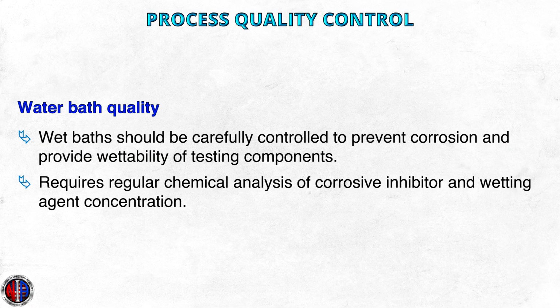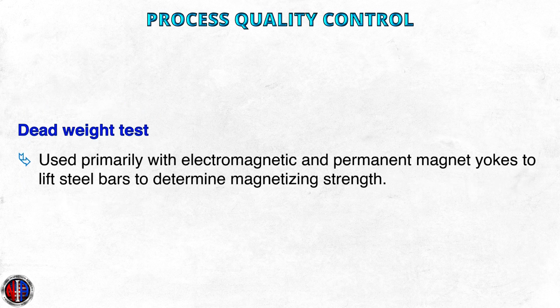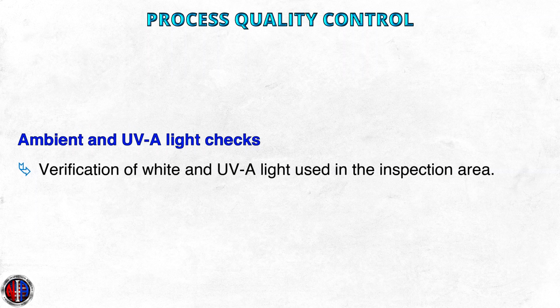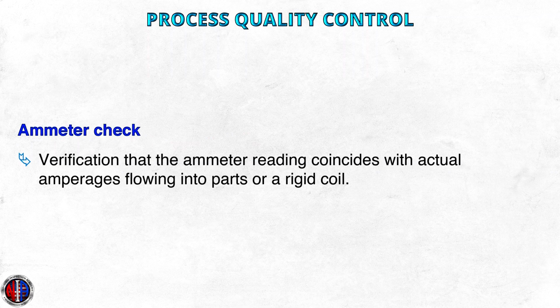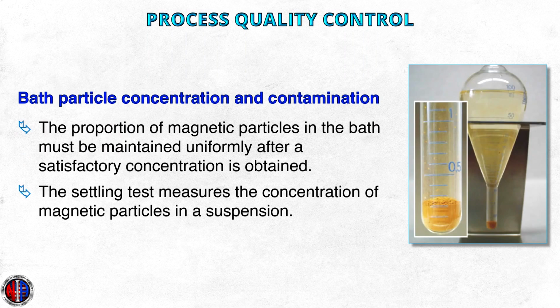Water bath quality. Wet baths should be carefully controlled to prevent corrosion and provide wettability of testing components. This requires regular chemical analysis of corrosion inhibitor and wetting agent concentration. The dead weight test. This test is used primarily with electromagnetic and permanent magnet yokes to lift steel bars to determine the magnetizing strength. Ambient and UVA light checks. This is the verification of white light and optimum UVA light used in the inspection area. The ammeter check. This check is verification that the ammeter readings coincide with actual amperages flowing into the part or a rigid coil.